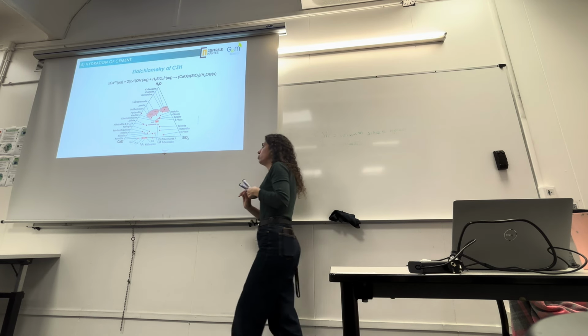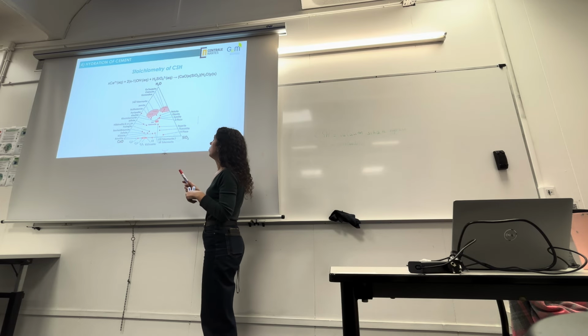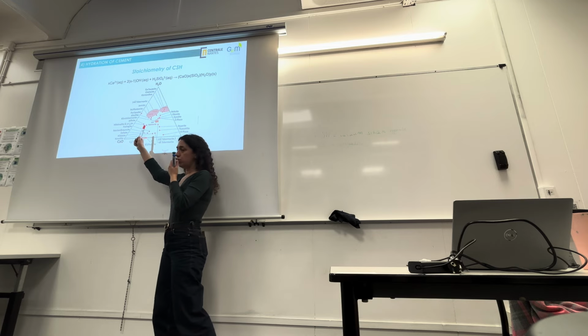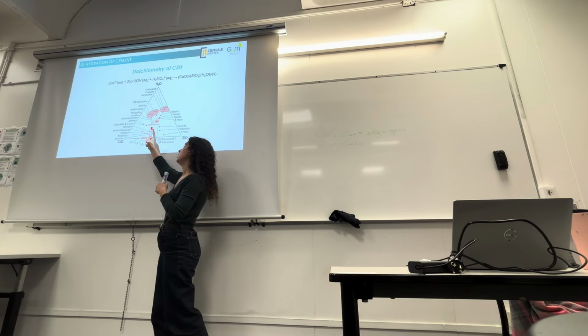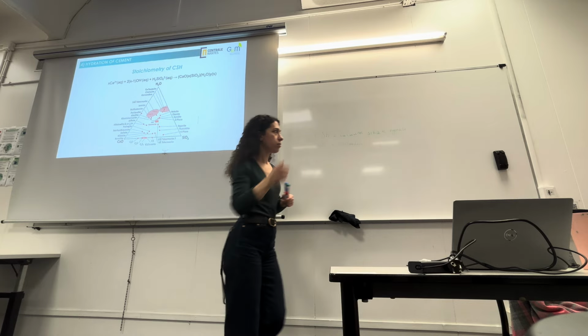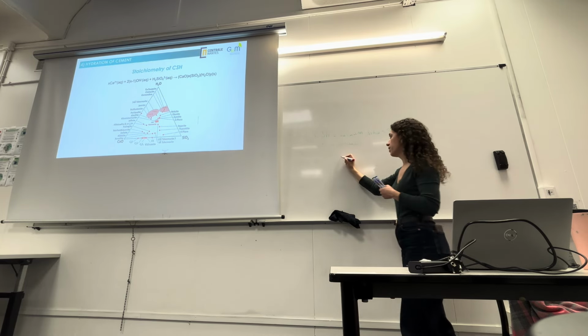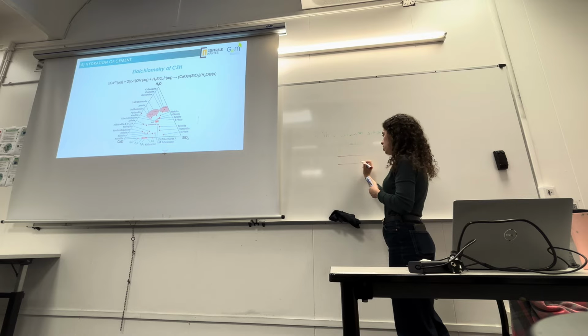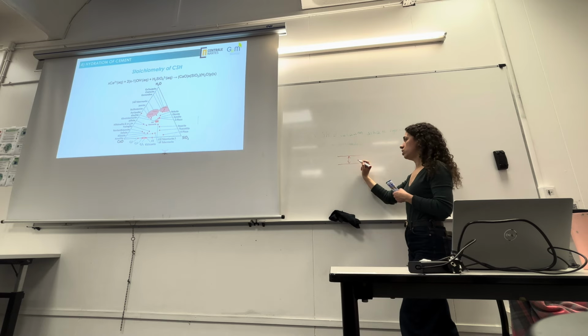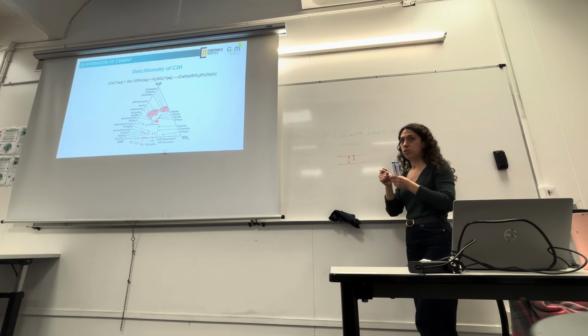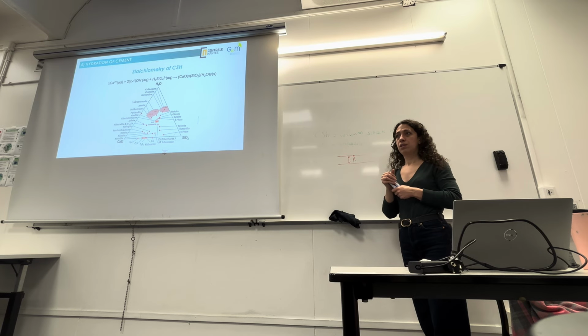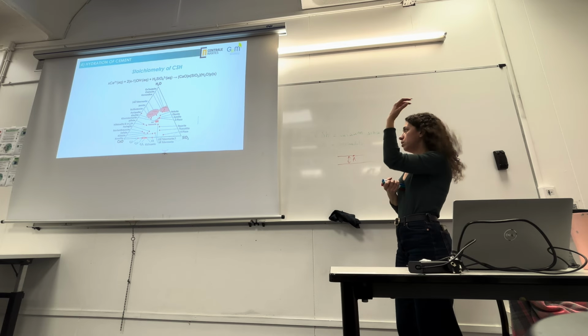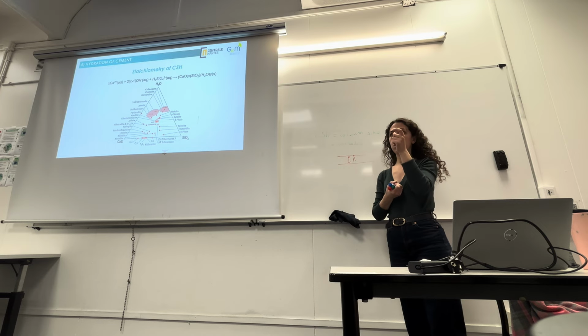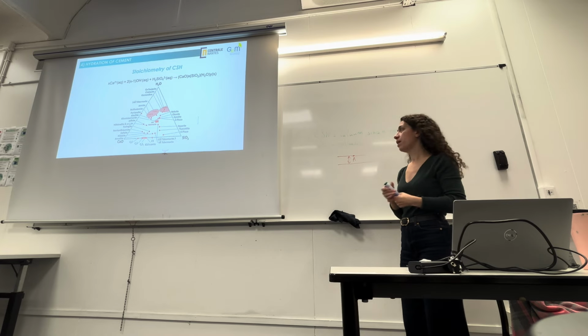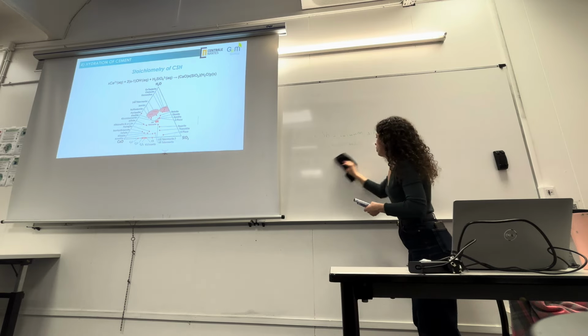Okay, so what we know is that the CSH from cement paste is quite close in geometry to what we call the specific CSH, that is tobermorite 11 angstrom. And 11 angstrom refers to the fact that CSH is composed of sheets, and the distance between those mineral sheets is measured in angstrom. You know what an angstrom is? 10 to the minus 10 meters. It's very used in chemistry because this is the size of an atom. So this is why we use angstrom.